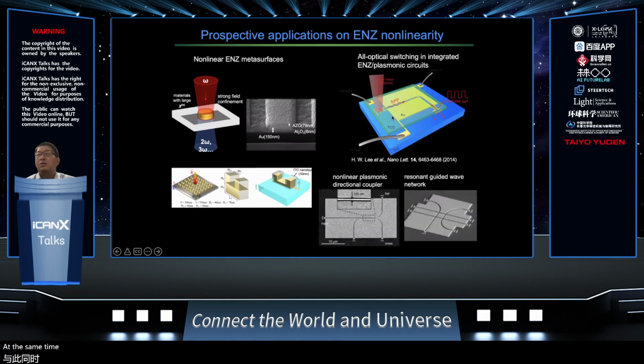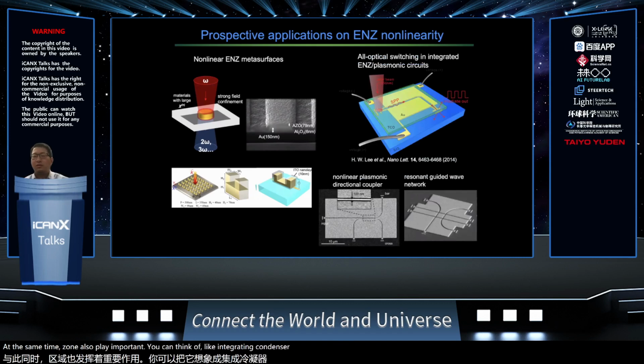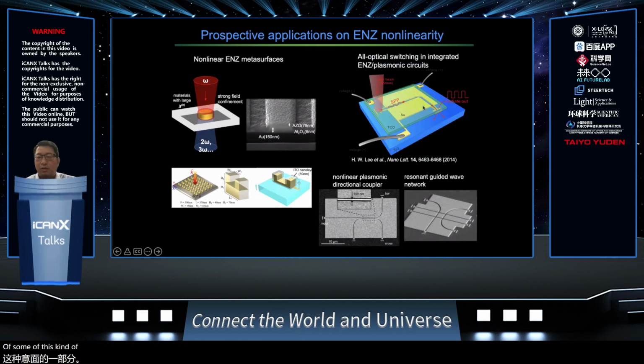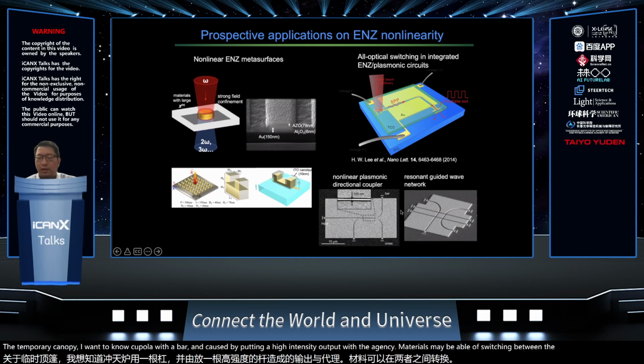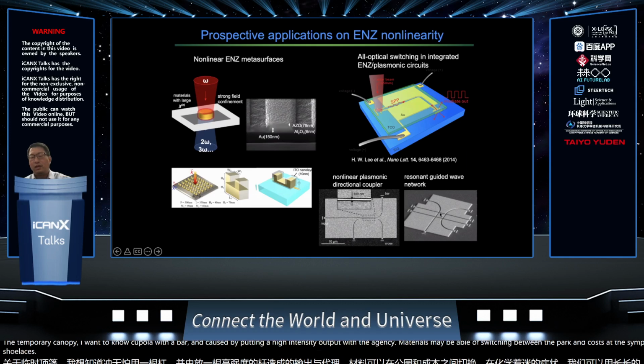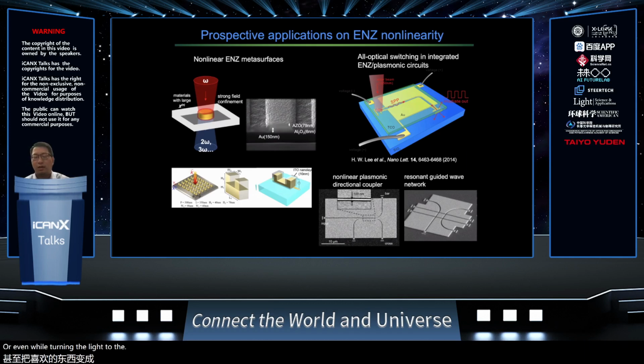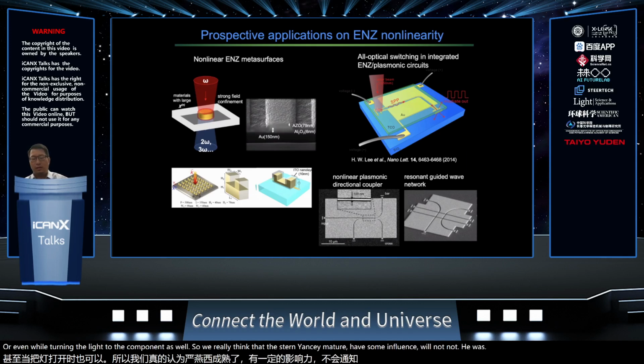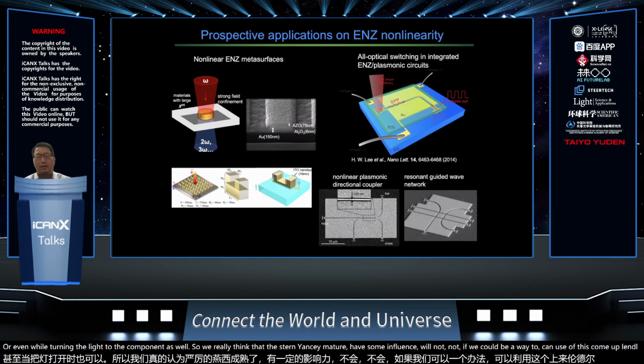At the same time, also quite important, you can think of integrating nanophotonic structures. For example, this kind of plasmonic structure, you can coat with this ENZ material, and by shining an ultra-fast light, you may be able to modulate the signal. So for example, you can have a directional coupler with a bar and cross. By putting a high intensity output with an ENZ material, you may be able to switch between the bar and cross. At the same time, if you have a compact wave resonator, you can use the nonlinearity to switch or even route the light to different ports as well. So we really think that this ENZ material has some enhancement on nonlinearity, which could really be put to use in this kind of nano device here.